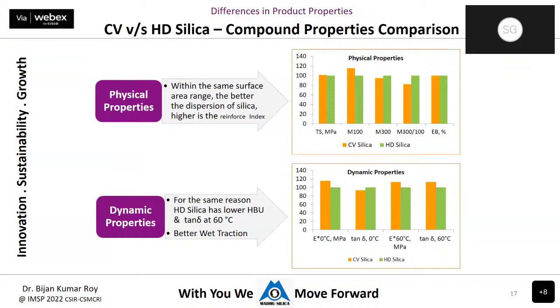The same is true for physical properties, that is the modulus, tensile strength, and elongation at break. Dynamic properties, as I said, are a mandatory requirement. All European countries are accepting only tires having low rolling resistance, that is the tan delta at 60 degrees centigrade. The lower the tan delta at 60 degrees centigrade, the better is the rolling resistance, or the better is the fuel efficiency. So with the highly dispersible silica, you will achieve better fuel efficiency at better or higher grip, that is the safety of the tire, as well as the modulus will be better for highly dispersible silica.